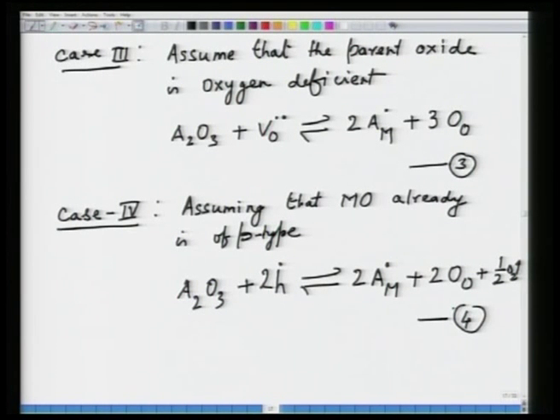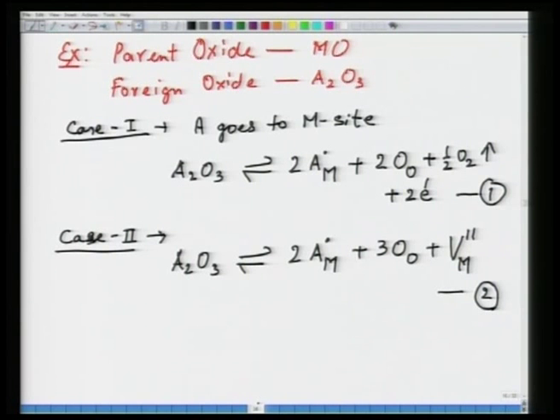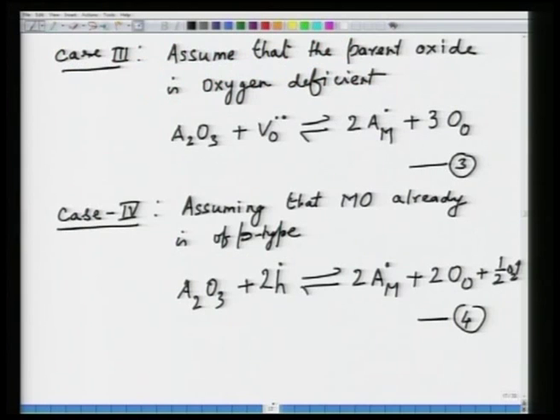So in the previous slide we looked at when the material was stoichiometric, it did not have any defect to begin with. Then what is the scenario? So you can have creation of a metal vacancy or creation of two extra electrons, or alternatively if the material was already oxygen deficient or contained holes to begin with, then these holes or oxygen vacancies could be compensated by the presence of these impurities. So as a homework you can do, for example, as an exercise